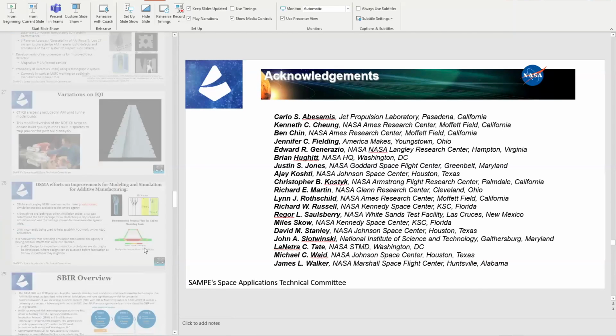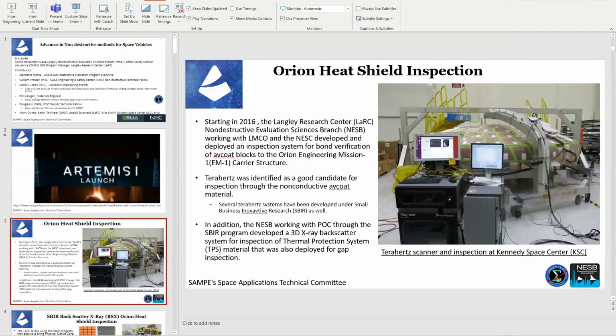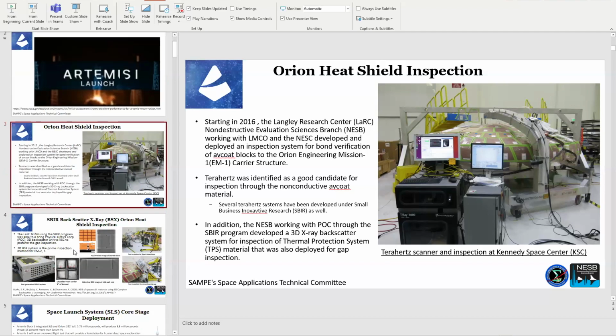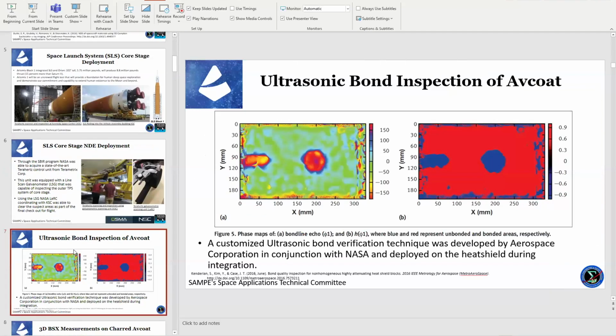Yeah, so there was two, and I'll flip back to the slide. I can't tell you exactly what they used, but essentially it's like a mastic, right? If you've ever tiled a floor or something like that, there was a mastic that goes down, and then the Avcoat tile blocks are pressed into that mastic. What we really wanted to be sure was that the mastic itself had adhered well. And that was done by the two methods that we talked about. The terahertz is covering the block acreage and looking for any major problems that would have occurred at that bond line. And then, of course, the actual bond verification was the ultrasonic technique, where you're using a stress wave that's going to have an issue where there isn't a mechanical connection to come back.